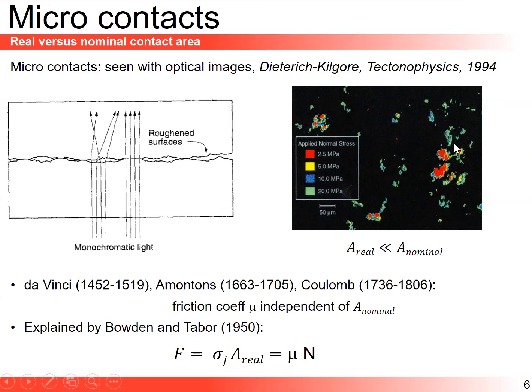The major consequence is that because of the roughness, the real contact area is much, much smaller than the apparent, also called the nominal, contact area. And this is a major finding that Bowden and Tabor in 1950 used to finally give a mechanistic interpretation of the friction coefficient and explain the Leonardo da Vinci experiment, and later Amontons and Coulomb, who observed that the friction coefficient mu is independent of the nominal contact area, but is really a function of the real contact area. The mechanistic understanding of Bowden and Tabor is that the total tangential force F is the product of the real contact area times the strength, the flow stress, that the contacting asperities can carry. And because the real contact area increases more or less linearly with the load at small loads, you get this linear relationship between F and N, which is this emerging Coulomb friction coefficient mu.